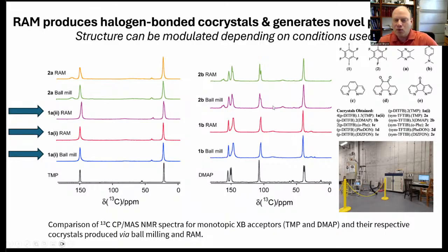And if you look at the top right, for example, product 2B, you can see the trace from the ball mill and the trace from RAM give essentially identical spectra, so the same product, the same polymorph. But if you look closely, you can see that the spectrum that we get from the RAM product has a bit better resolution, with sharper peaks, both in the middle peak and on the left. And this is a measure that we're getting better crystallinity from the RAM product. Okay, so perhaps a degree of amorphization coming from the ball mill.